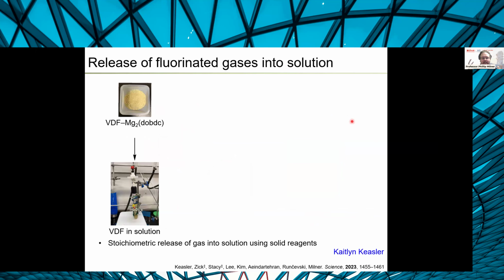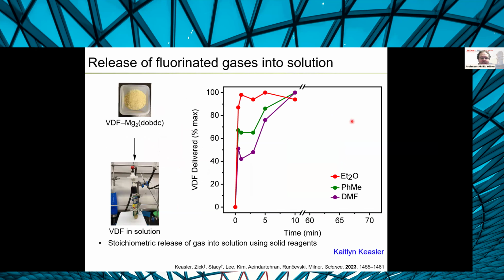And so what Caitlin did was try to see if we could load up a gas inside a MOF and then release it into solution by just dropping it into solvent and looking by fluorine NMR to see if the gas came out. And in fact, we were able to see that it comes out quite quickly from this MOF, regardless of the polarity of the solvent we use. It saturates the solution in about 10 minutes. And so we have achieved at least a goal of being able to handle a gas as a solid and throw it into a reaction.